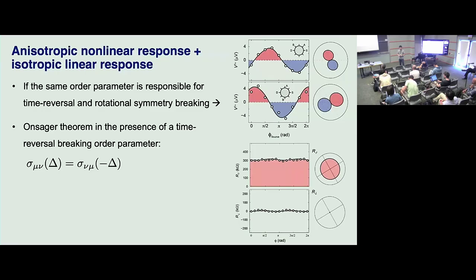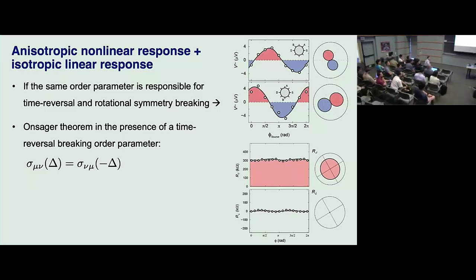I see, how low is it? I think out of maybe 10 samples, 3 or 4 show very uniform response. I see, thank you. Any last question? Hey, Leo. It's about 2 micron in diameter of the disk. And we intentionally make it very small to minimize inhomogeneity.